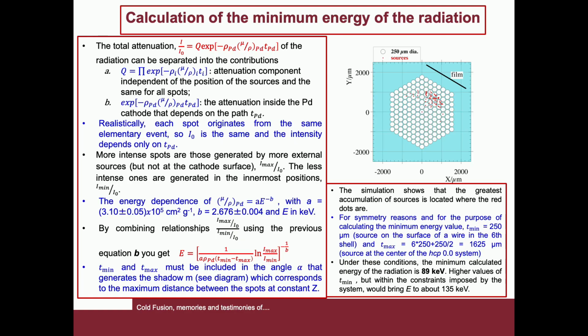The maximum is set equal to 1875 minus 250, that is 1625 microns, which is the source at the center of the HCP system. Under these conditions, the minimum calculated energy of the radiation is 89 kiloelectronvolts. Higher t minimum values, but within the constraint imposed by the system, would give a value of about 135 kiloelectronvolts.